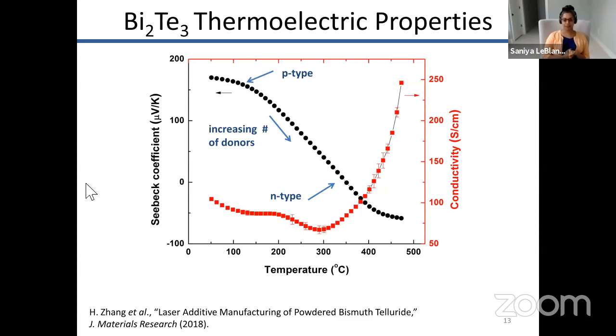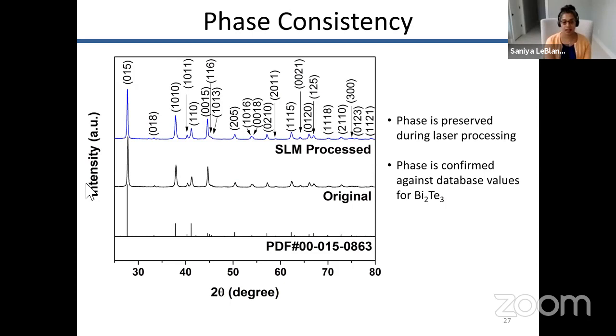And what that tells us is that something is happening during laser processing that's impacting the structuring that then impacts how the carriers move through the material. It's changing the transport of the electrons through that material. And so we thought, oh, okay, maybe it's changing the phase of the material. But what's really interesting is if you look at the X-ray diffraction results, the original material, which is the one in the middle, that's the starting material, actually lines up with the laser processed material. And so what we see is that the phase is actually preserved during laser processing. We're not changing the material phase. And so the change in transport property must be coming from something other than a change in phase, or a change in phase that can be detected from X-ray diffraction conducted on the entire material.